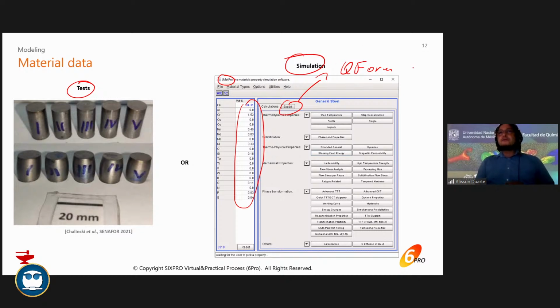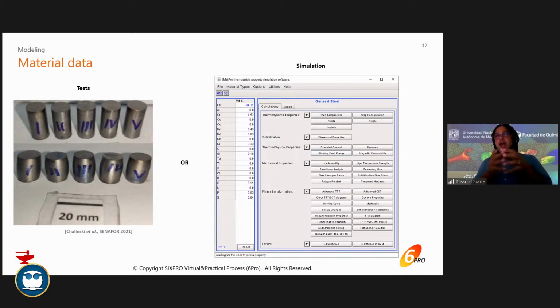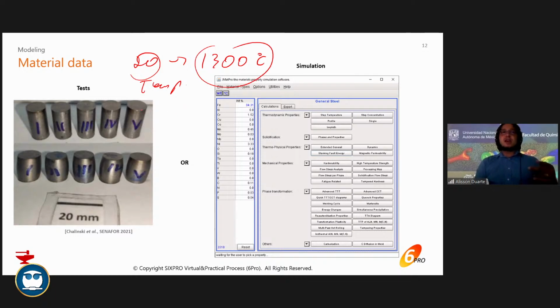QForm presents us a very large amount of material already in the library. But here it's important to say this is only the flow stress. So I need this for different temperatures, okay? From 20 to, let's say, 1300 Celsius. And also for each temperature, I need, let's say, at least 6 speeds to have a wide range of behavior for that material.